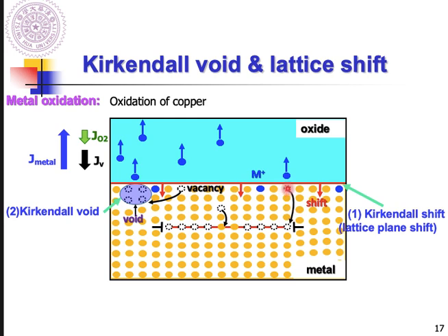The vacancy probably will diffuse to replace the atoms located at the edge dislocation. As long as we have enough vacancies, and the vacancies replace this whole edge dislocation, the edge dislocation is going to disappear, right? So this will drive the plane shift downward.